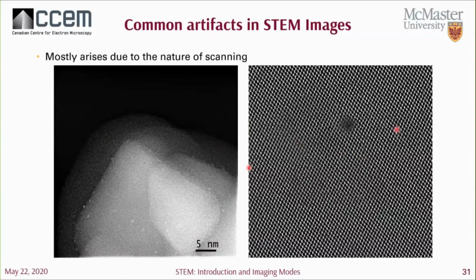So here we see a buildup of a carbon layer on our sample. If we continue to collect multiple frames or multiple images, we would actually see the thickness of this carbon layer increase, just get thicker and thicker. This carbon layer obviously decreases your signal to noise ratio, and it doesn't give you good imaging.